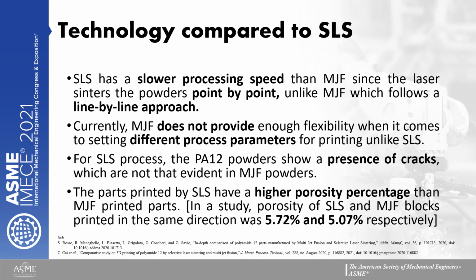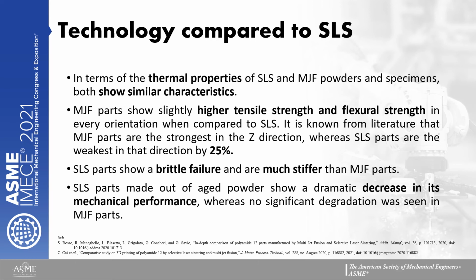The parts printed by SLS have a higher porosity percentage than MJF printed parts. In a study, porosity of SLS and MJF blocks printed in the same direction were 5.72% and 5.07% respectively. When it comes to the thermal properties, both show similar characteristics. MJF parts show slightly higher tensile strength and flexural strength. SLS parts show a brittle failure and are much stiffer than MJF parts. SLS parts made out of aged powder show a dramatic decrease in mechanical performance, whereas no significant degradation was seen in MJF parts.